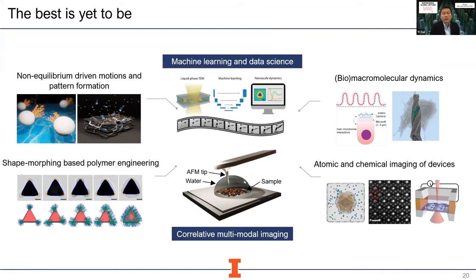Yeah. Well, Chen, speaking of your biological sample, the nanodisc, what's the total dose? You say you can observe about 2 minutes. So what's the electron per angstrom squared of dose accumulated over time? Right, that's a great question. So I can first say the dose rate we use is just about several electrons per angstrom squared per second. And then in accumulating this movie, indeed we capture up to minutes.